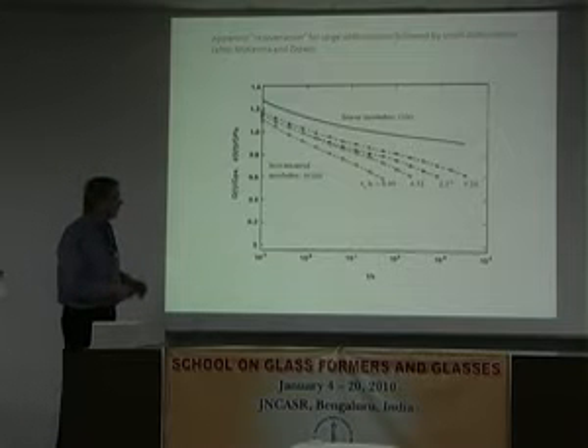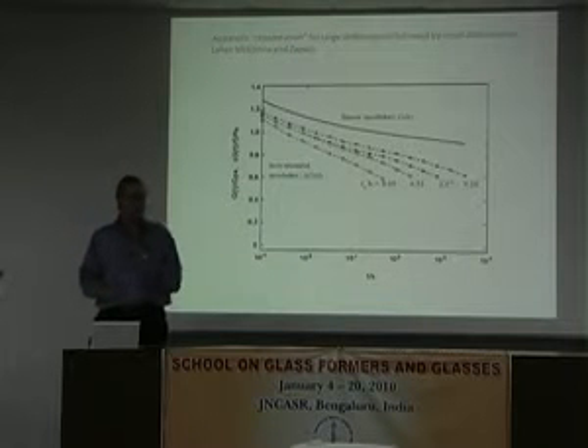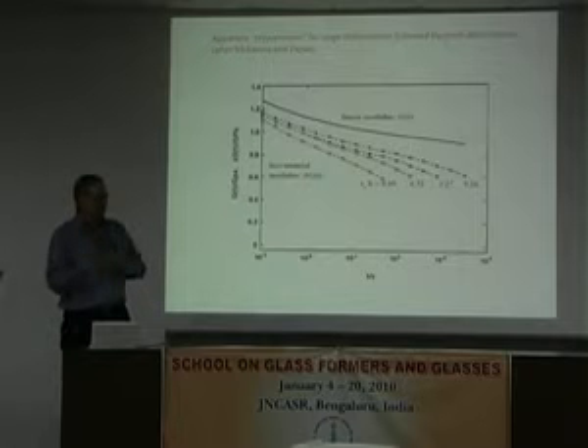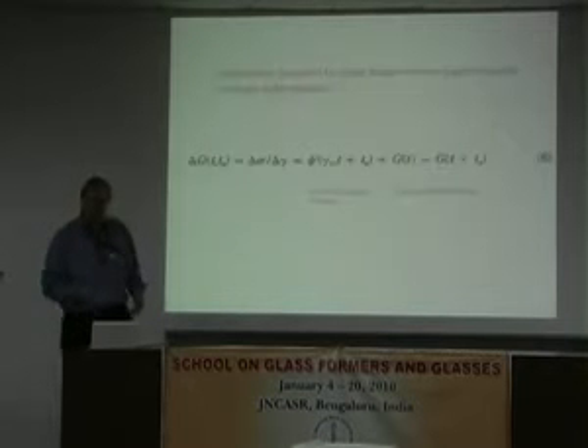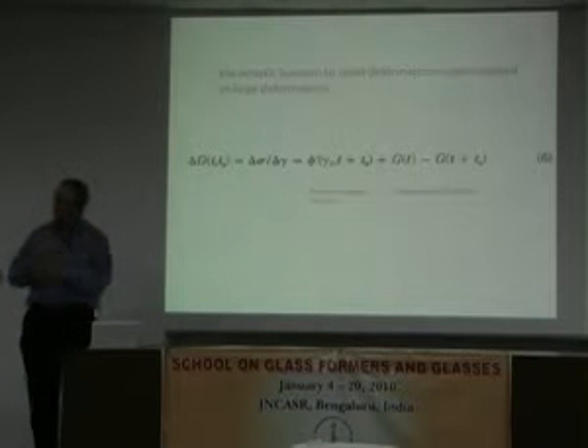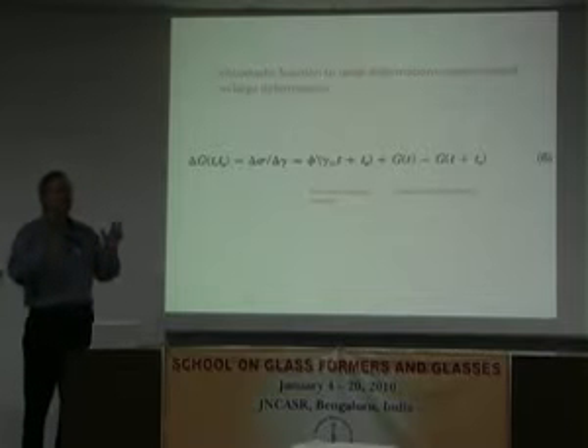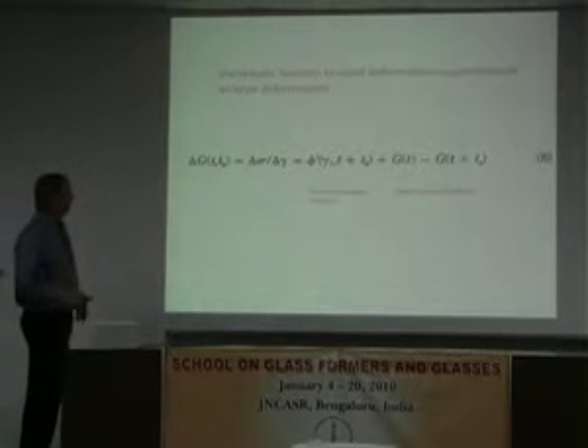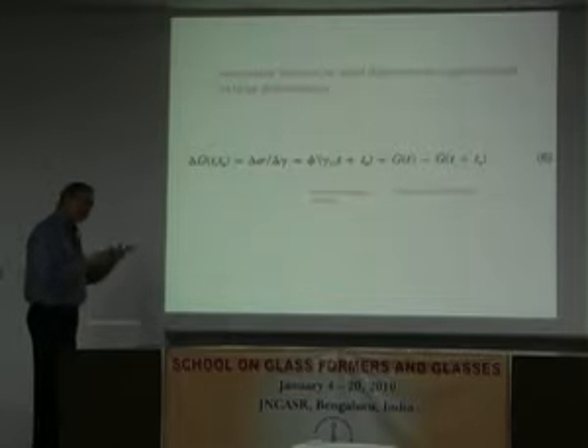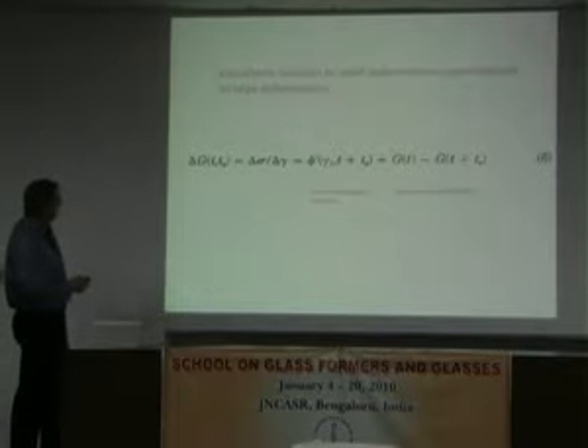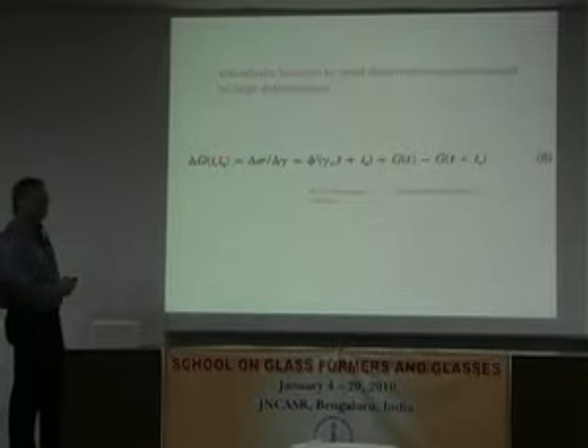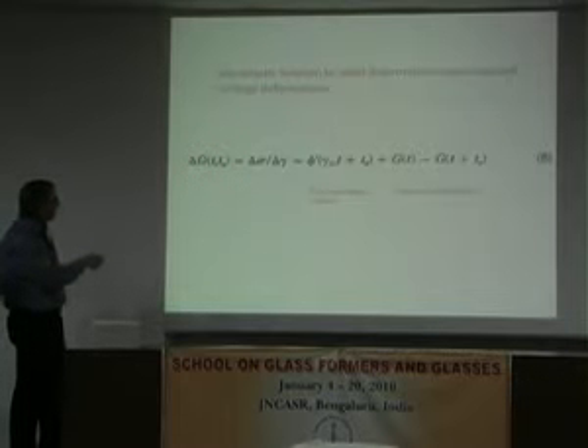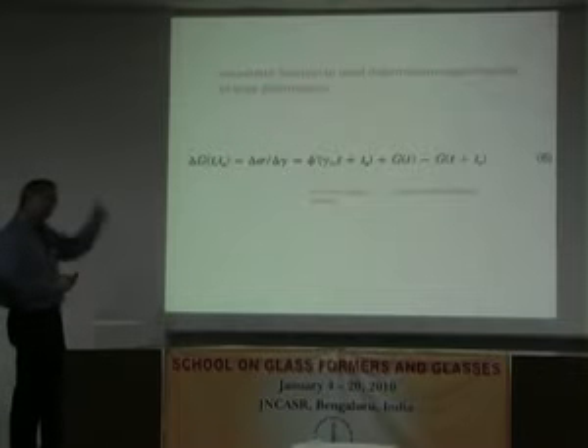Now we said we think this is a very complicated experiment because we know a lot about viscoelasticity. So we actually solved a nonlinear viscoelastic constitutive law to see sort of what you might expect in this kind of experiment. And I'm not going to go through the details of it, but it comes out of nonlinear viscoelasticity. And again, another two-time function. So we get the incremental modulus at time and aging time after we put the big strain on.